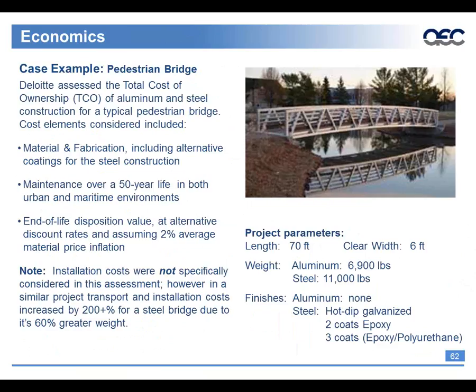Case in point on this, a pedestrian bridge. Looking at the total cost of ownership of a bridge, you have material and fabrication taken into account of this, alternative coatings for the steel, a 50-year life expectancy, end-of-life disposition value. And so, at least in terms of this case study, it's basically material, fabrication, coatings, not installation cost. Although in this particular case study, because you've got a little more than half the weight than you would in the steel, bringing the material to the site probably costs you less with the aluminum than it would with the steel. And so essentially a bridge, 70 foot long, 6 foot wide, no coating on the aluminum, so mill finished, and a couple different coatings on the steel. Next slide.